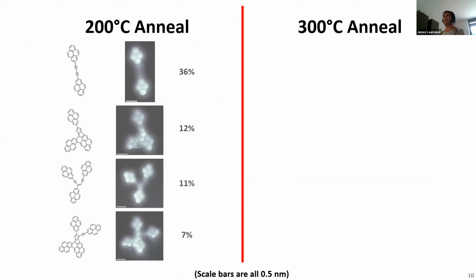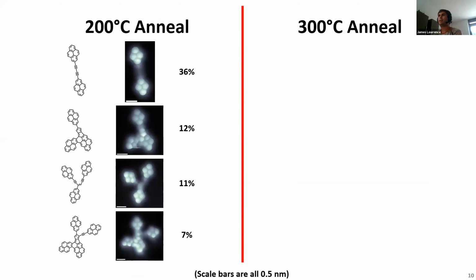So if we look at the most common products on the surface, at 200 degrees, we can use this high resolution STM with CO tip to identify some of the more common products. So at the top here, there's this very straight Glaser coupled dimer where there's a single bond between these two alkyne groups here. We've also got this very fused trimer here, and then also these open trimers here, as well as some derivatives of the fused trimer. So these three products are particularly important to what we'll talk about in a couple of slides.